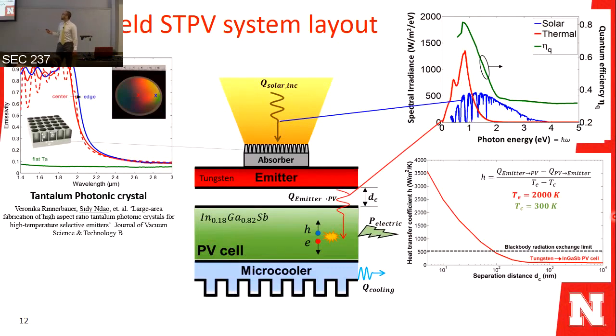The solar radiation in blue here has a very wide spectrum, and it does not target the peak of the efficiency. If you just introduce the emitter between the sun and the PV cell, you are tailoring your spectral heat transfer and making it align with the peak of the efficiency of the solar cell. So you have both the advantage of increasing the power density and increasing the efficiency.